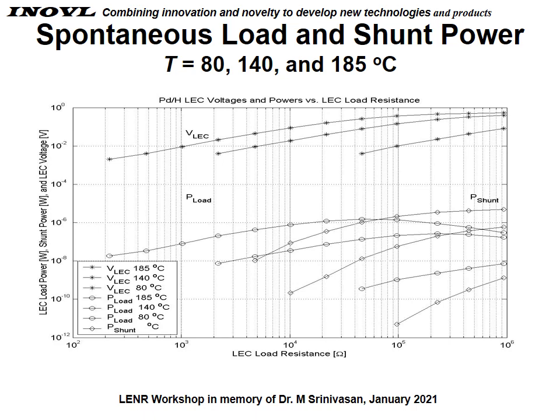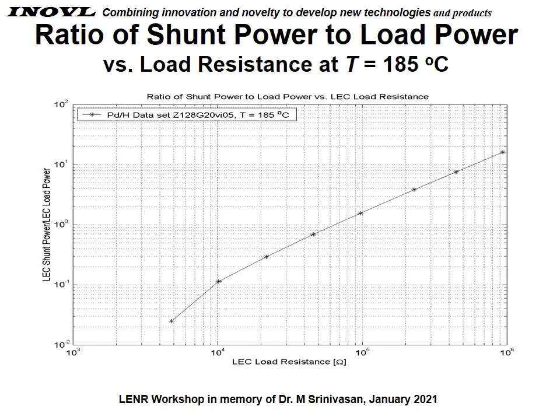Spontaneous load to shunt power. This is an interesting plot because as we look at this, what you see is that the shunt current goes up higher than the load current at the higher load resistances. We were interested in determining the ratio of the power going into the shunt relative to the power going to the load. Here we have it for load resistance at a temperature of 185 degrees C. And what you see is the shunt current is going up, the ratio is going up, and so in effect, in one of our calculations, 17 times more power was going into the shunt than going into the load.